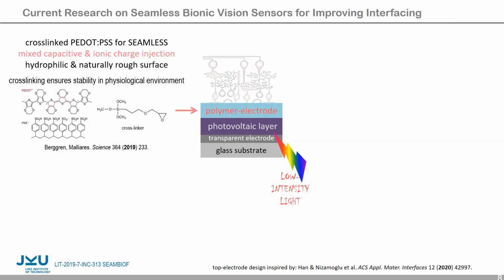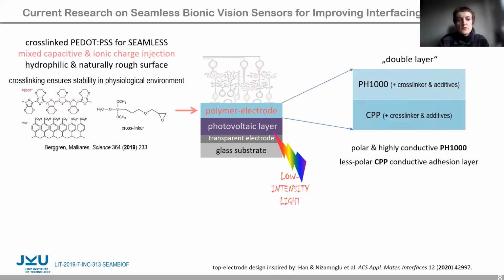This polymer electrode swells in water and soaks up ions from the electrolyte. By this, it is capable of a mixed capacitive and ionic charge injection into the electrolyte. Ionic conductance is the natural charge transport mechanism of neuronal cells, which makes this polymer electrode a very promising candidate for a seamless charge mediator. We have worked out a preliminary electrode design, which is the double layer design.